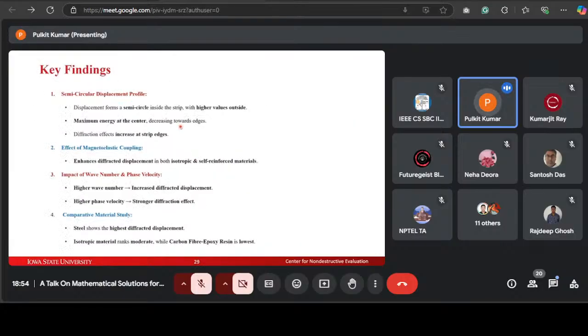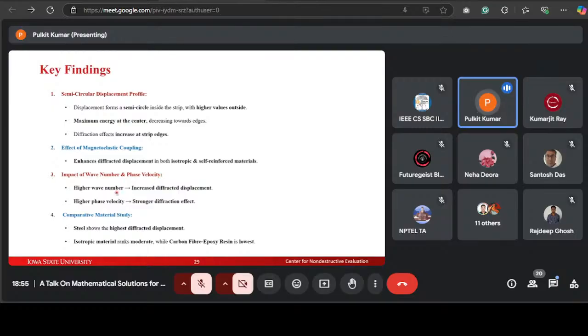So what are the key findings of this study? We have a semicircular displacement profile in the middle. The displacement forms a semicircle inside the strip with higher values outside, and the maximum energy is at the center and decreases towards the edges. The diffraction effect increases at the strip edges. And what is the effect of the magnetoelastic coupling? It enhances the diffracted displacement in both isotropic and self-reinforced material. For the wave number and the phase velocity, a higher wave number means a higher diffracted displacement, and a higher phase velocity means a stronger diffraction effect.